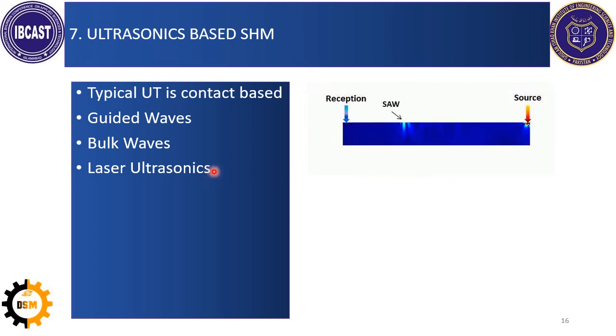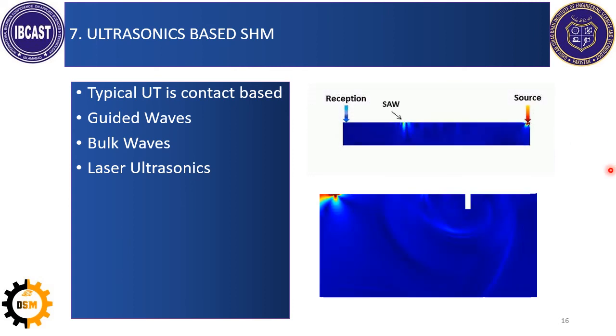Laser ultrasonics is a modification of ultrasonics in which you use a laser as a source. It is a pulse laser which produces high frequency ultrasound in the surface, and then you can use an LDV, for example the laser Doppler vibrometer, to receive those. This is known as laser ultrasonics. These typically produce bulk waves, and these are good for short distances. This is another example where you can see the surface waves produced on the surface and on the complex geometry. These are reflected back as many other different types of waves.